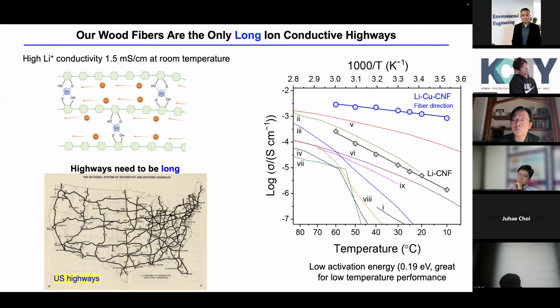So it's basically like a freeway system, and because the fibers are very, very long, you only need a little bit of them to conduct ions. The plot on the right side shows the activation energy is very low, which means this fiber actually has very good performance at low temperature. So you don't have the typical glass transition temperature of polymer electrolyte.